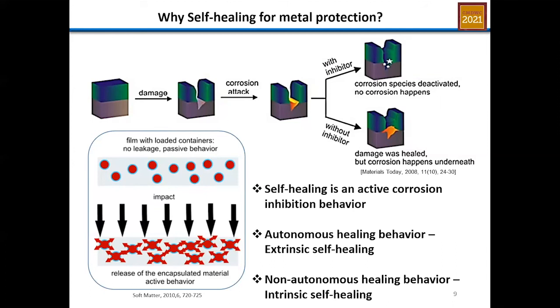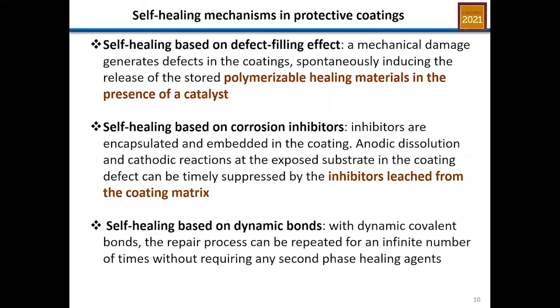And that's what leads to the active, inhibitive behavior of this in the scratch plane. So when we talk about self-healing, it's actually an active corrosion inhibition behavior that should occur within the scratch plane. And it could either be autonomous healing, which is related to the extrinsic self-healing, or it could be non-autonomous, which is related to the intrinsic self-healing. So various mechanisms have been studied and reported.